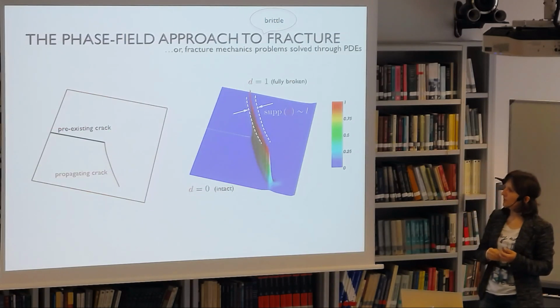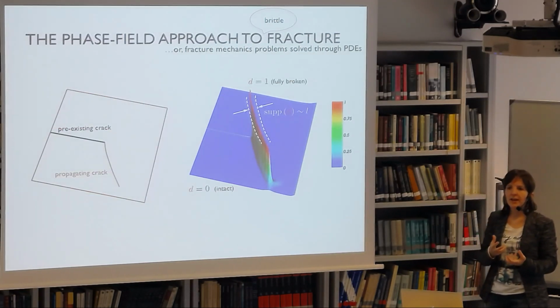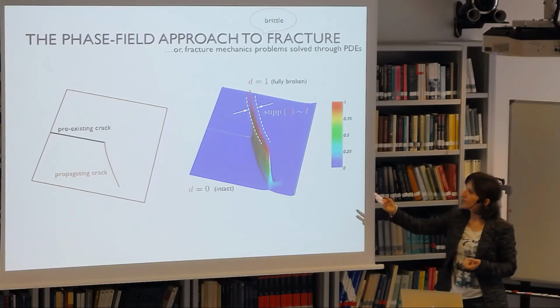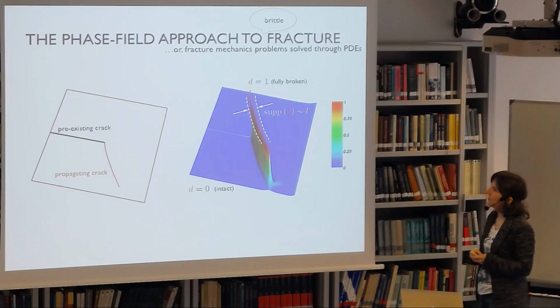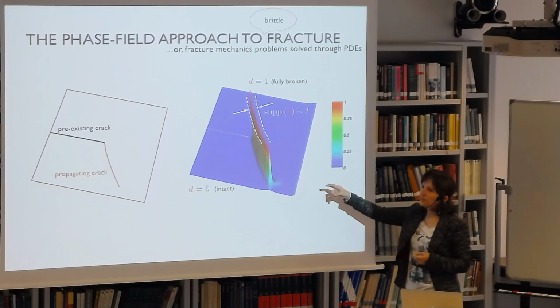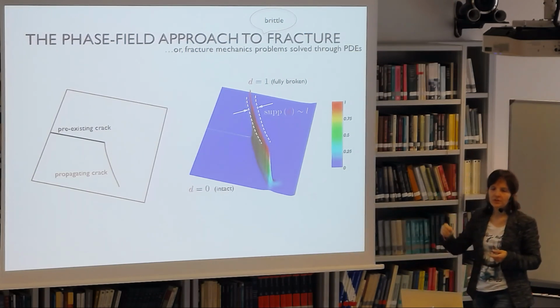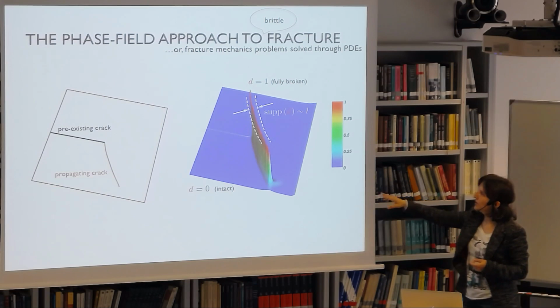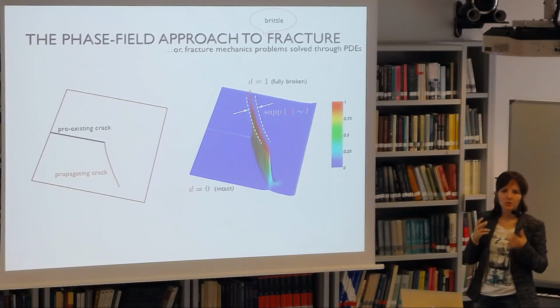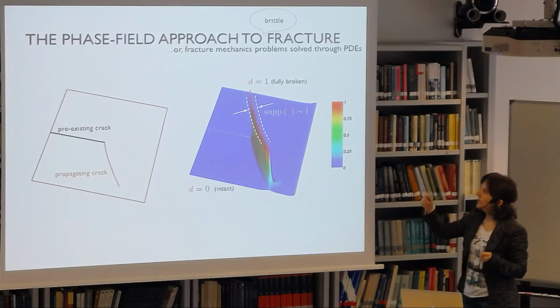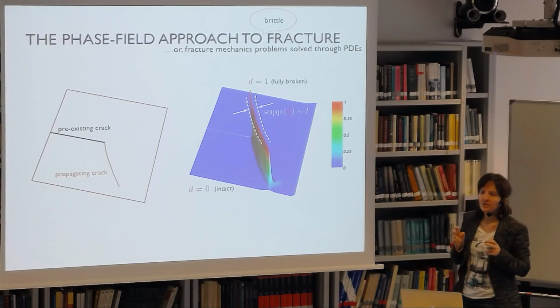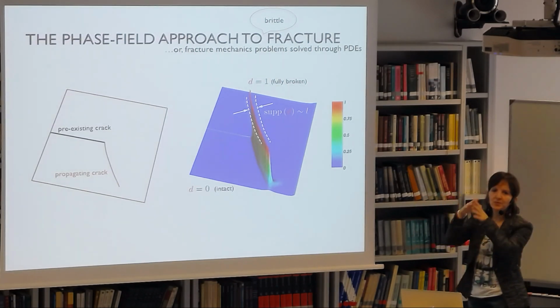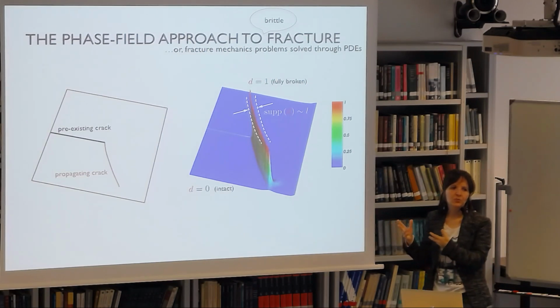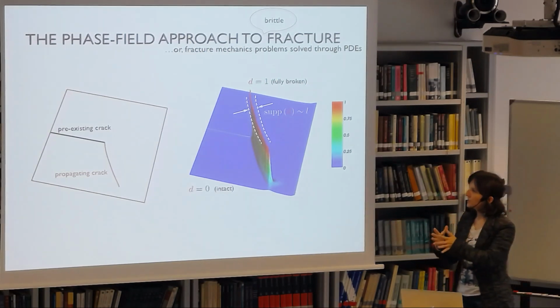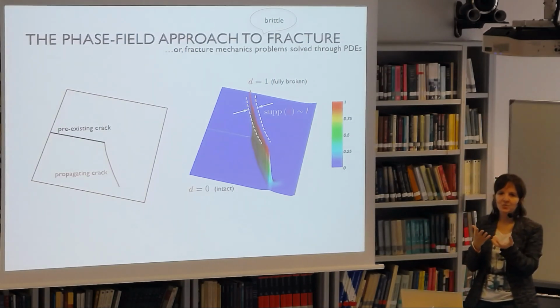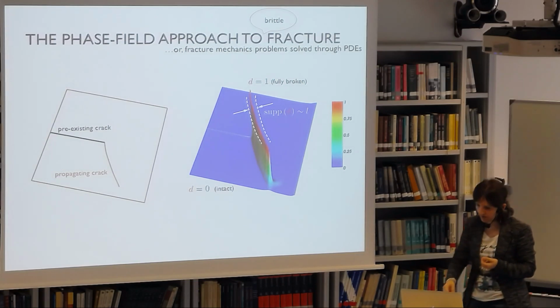Now, this is, let's say, a graphical interpretation of the regularization through this parameter L. So if you have a propagating crack that you want to describe through the phase field, what will happen is that you will have a very steeply varying phase field D, which will be equal to 0 wherever the material is intact, and will steeply vary between 0 and 1 in the vicinity of what you consider to be the crack. So basically, D will be equal to 1 along the axis of the crack. And the width of this smeared approximation of the crack, in a sense, is proportional to L. So the smaller L, the closer your smeared crack approaches the, let's say, sharp crack that you would like to approximate. And so this is a very immediate interpretation.